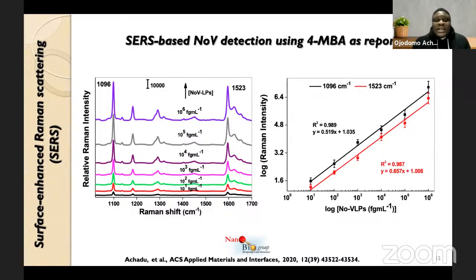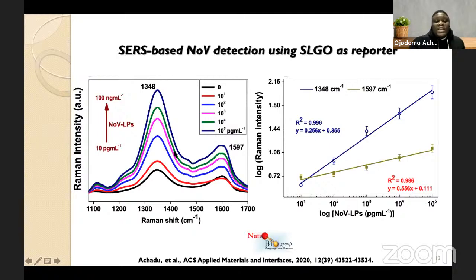So in addition to using the reporter alone, we decided to also use a system whereby we did not conjugate the 4-mercaptobenzoic acid reporter to the substrate. Rather, we used the characteristic D and G bands of the 2D graphitic substrate as the capture substrate as well as the reporter. However, we see that the sensitivity of using this 2D graphitic substrate alone without the Raman probe is not as high as that of the reporter. This is due to the fact that the Raman reporter, based on their small size, can experience higher plasmonic coupling compared to the 2D graphitic nanostructure.